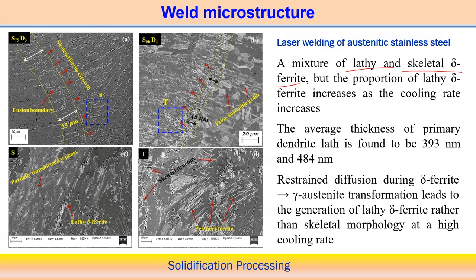Actually, the delta ferrite structure is the high temperature phase. During the cooling phase we can get a mixture of lathy and skeletal delta ferrite, but in this case the proportion of lathy delta ferrite increases when the cooling rate increases. So this is the correlation with the microstructure: when the cooling rate increases much more, we get more delta ferrite, more lathy delta ferrite. Lathy means it's a morphology, so this delta ferrite is much more in this case.